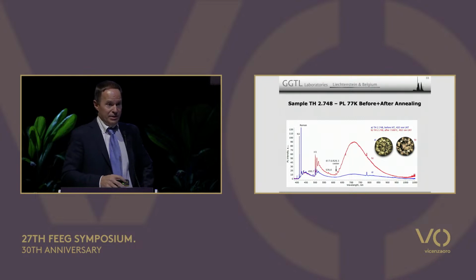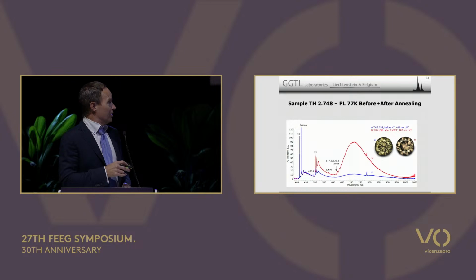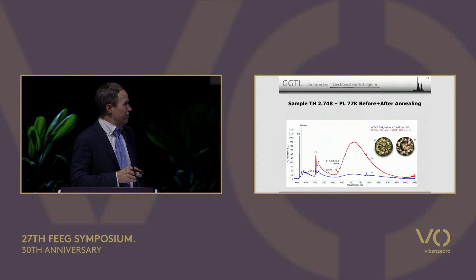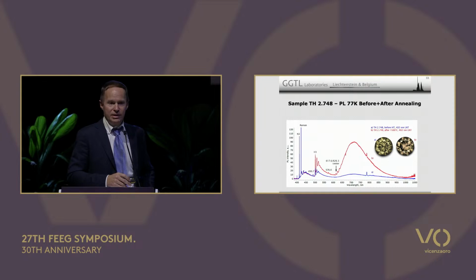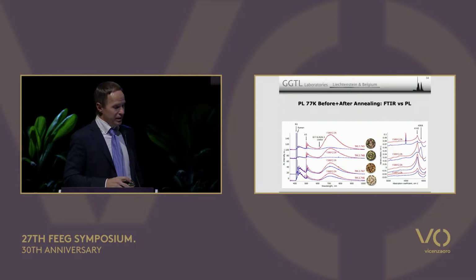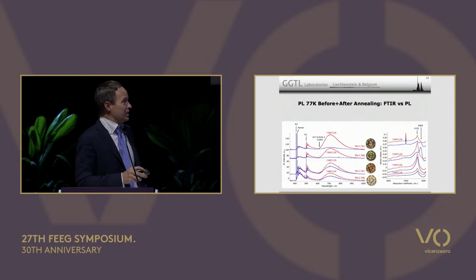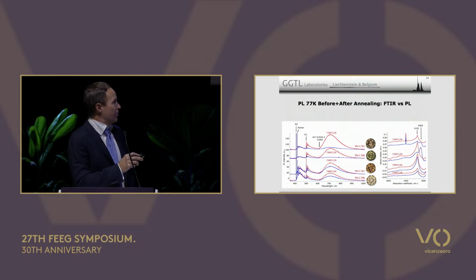And in luminescence, I said before, in browns, we have this strong center at 617. Well, before the treatment, the center is practically absent, and after 1500 degrees, we form a very strong center at 617, 626. After 1800 degrees, it just decreases a little bit in intensity. And this worked for all samples. So in all samples, we basically shifted, the 4068 was gone after heat treatment at 1500 degrees Celsius. The ones that did not have a 4068, not much happened. Okay? So there is a clear-cut correlation between the 4068 and 4165, and also the formation of this strong luminescence band here.